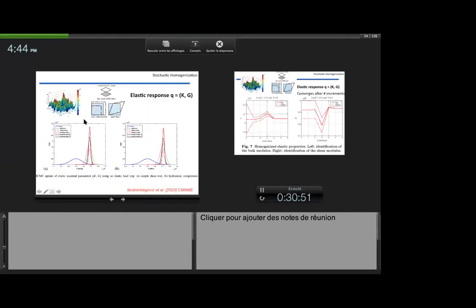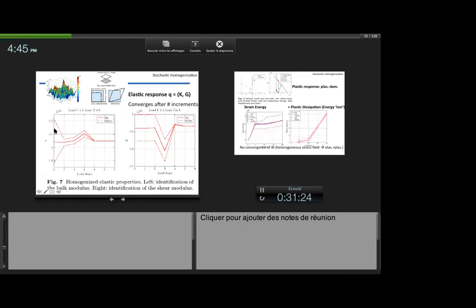How does it work? Well, if you're interested in identifying the probability distribution of these elastic coefficients like bulk modulus K and shear modulus G, you can see that it does converge very quickly. In fact, it converges so much quicker if your prior is better. So sometimes rather than taking this prior, blue, which is an expert opinion, and maybe this expert doesn't know everything, so he gives you a very large standard deviation. When you do the first computation, you can take this computation result to be a new prior, and you get better and better starting points, so you go into convergence much more quickly. And you can see also here, this is the same type of result, only presented with the confidence interval, the 95%, let's say, this type of results.